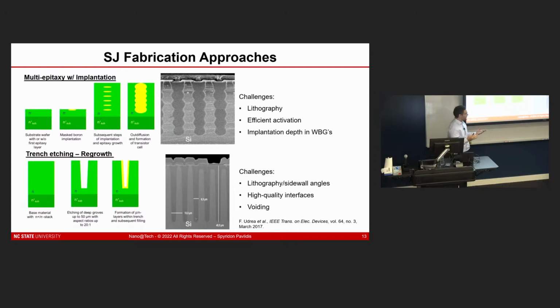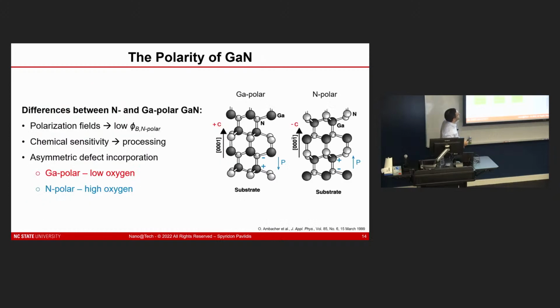And we can't do wet etching in GaN, and we have to use dry etching. Those dry etching processes usually leave behind some type of damage. Those interfaces are going to have defects, and then those can be leaky interfaces, and then also lead to problems with the device performance. So with GaN, it's really hard to look at what people have conventionally done and just do a one-for-one swap for processes. We have to think about a new way to handle this.